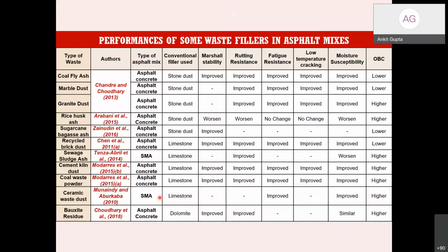This is only one slide for the literature review. There are so many ways which have been worked upon in the literature. Okay, there are many more. I could not quantify all in this particular slide, but there are many more. Okay, so there are coal fly ash, marble dust, granite dust, rice husk ash, which is an agricultural waste, sugarcane bagasse ash, again an agricultural waste, recycled brick dust, again a construction demolition waste, sewage sludge ash, cement kiln dust, coal waste powders, ceramic waste dust, bauxite residue, all such things have been used. And mostly you will see that the use of such waste fillers has improved the properties. Only in certain cases, at one or two places, one or two properties have reduced. Okay, it has worsened the properties. Most of the properties have increased.